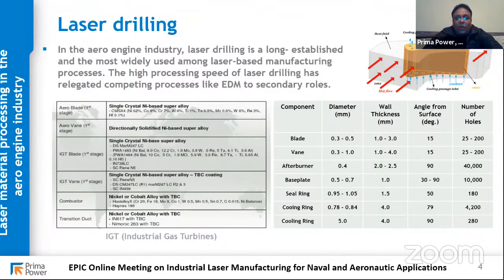If you look at the hole drilling, these are some of the components: blade, vane, afterburner. These are typical diameters. You tend to drill 0.3 to 0.5, and then there are typical thicknesses. And there are a number of holes, anything from a few hundred up to 40,000 holes drilled currently using lasers.